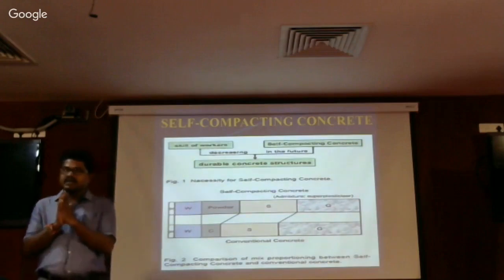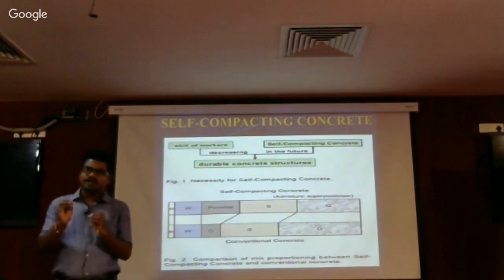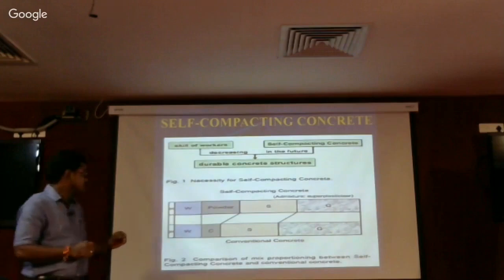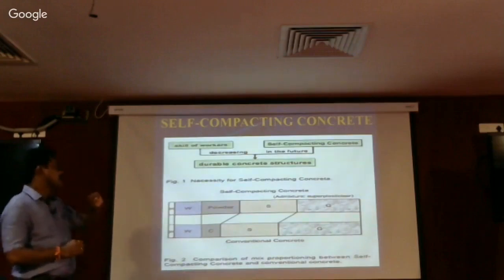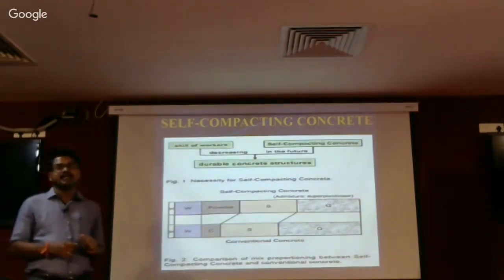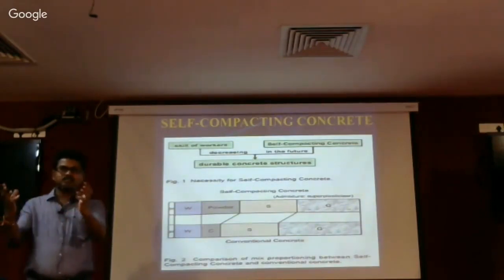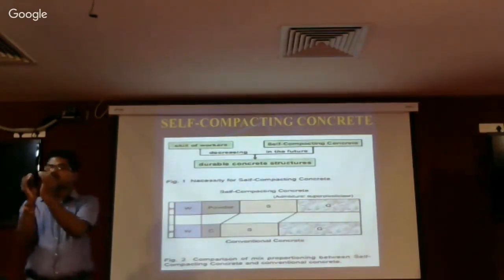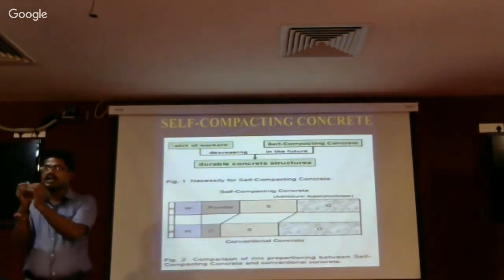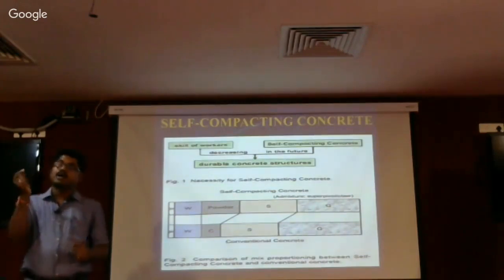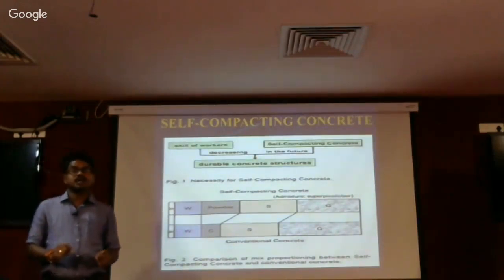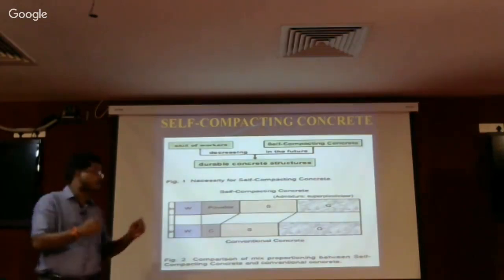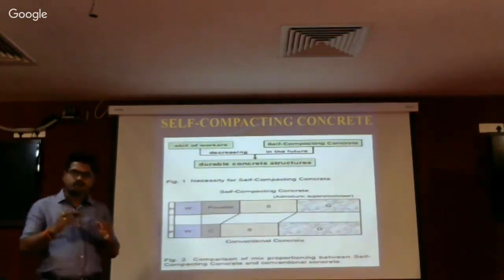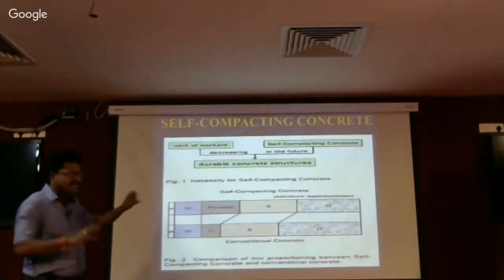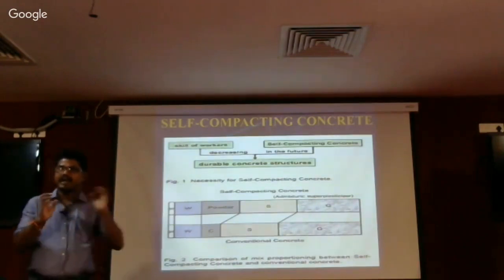Then, because here I am trying to fill the voids with the fine powder, the sand content is more than the coarse aggregate content. Because the concept in the preparation of concrete is, whatever the voids formed by the coarse aggregate are filled with the sand, and whatever the voids are there in the sand are filled by the powder. So here fine materials, just like fine aggregate and powder.